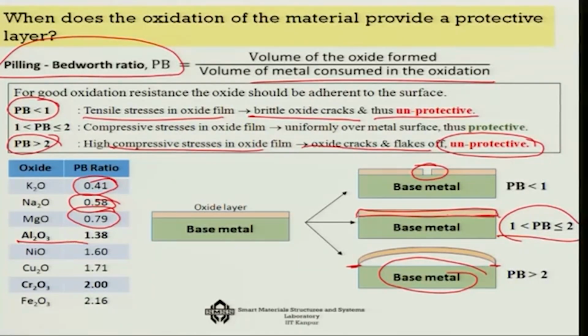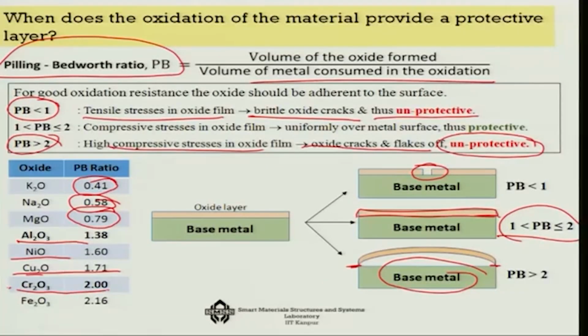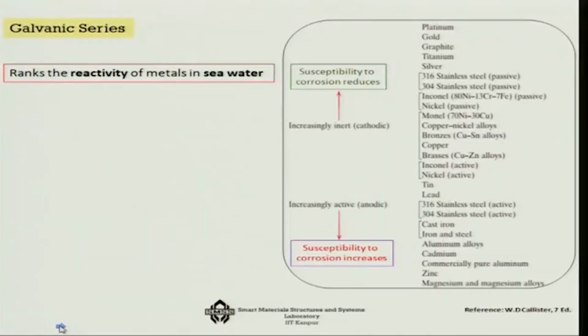That is why aluminum oxide layer is used in many cases as a good protective layer, and aluminum itself is also much better in terms of corrosion, because a part of aluminum is sacrificed for aluminum oxide formation, and that gives good nice coating of the pure aluminum. Then there is the other ones which are gradually going, like chromium is possibly the last one. Beyond chromium it is greater than 2, and hence you cannot use it as a protective material. So, thus the PB ratio works like a nice guidance in terms of choice of the material.